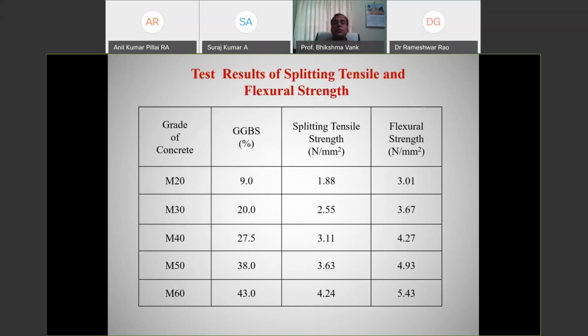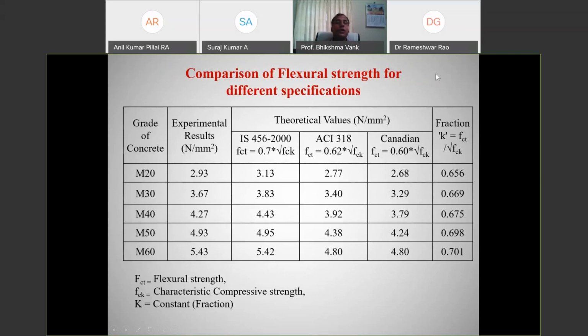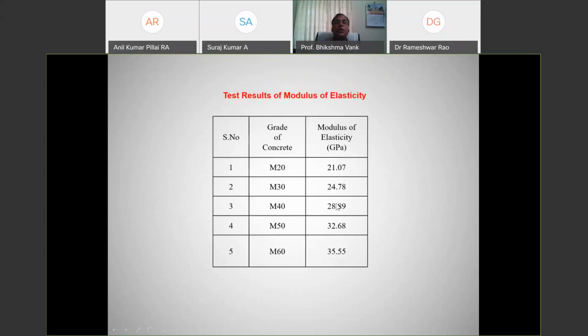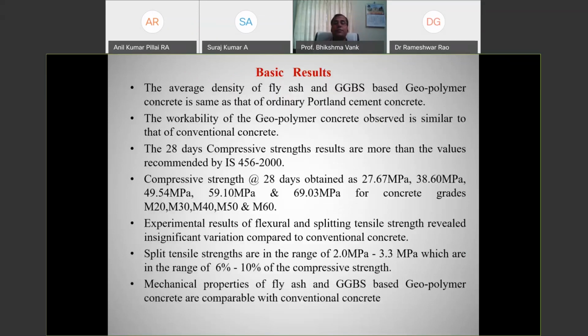So these are the splitting tensile strength values, and flexural strength values also we got, and we have checked these values with the Indian standard codes and other codes also. With IS 456, flexural strength is 0.7 root fck. With these values being compared, they are within very acceptable limits. ACI code, Canadian code, all these codes we have checked. Results of modulus of elasticity also checked, and it is within the acceptable limit.